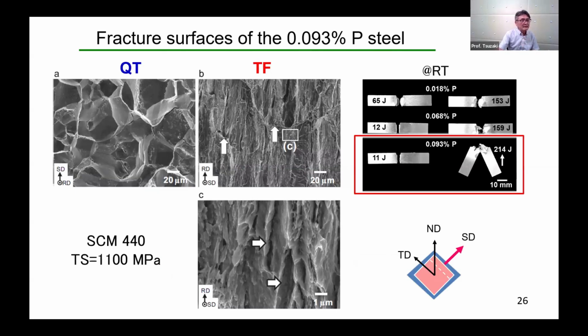Okay, let me continue. So this slide, number 26, shows fracture surface of the 0.093% P steel. The intergranular fracture occurred along the boundary of the prior austenite grains of the QT sample. In B and C, you can see SEM micrograph of delamination plane of the TF sample. Fracture mode of the delamination planes is characterized as a mixture of quasi-cleavage and intergranular fracture indicated by arrows like this.